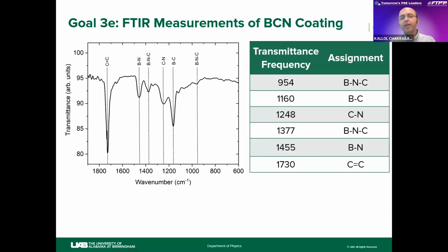Next, we performed FTIR to see what is present in the coating. According to the FTIR, we again see CC bonding, BN bonding, BNC bonding, CN, and BC bonding in our synthesized coating. This also suggests that our coating is a ternary coating, since we are getting the BNC coating, and our sample is carbon-rich boron carbon nitride—the CC peak intensity was highest here.